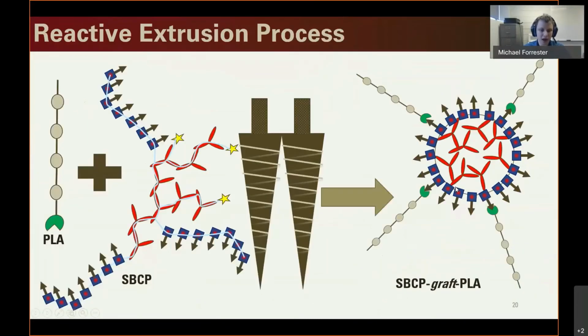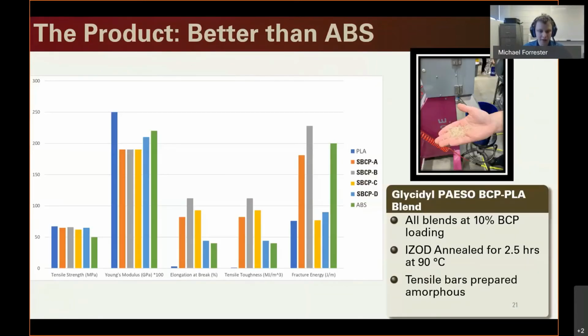And so that was then compounded in the Haake system with polylactic acid. And the thought was that if we were doing what we wanted to, the reactivity of these glycidyl groups here would allow grafts of PLA to form, and some nice micelles with good interfacial interaction would be generated. And the mechanical data certainly seems to support that that is occurring. And this particular plot shows a couple of different formulas of that block copolymer we produced. These are increasing glycidyl initial molecular weight blocks. These are all at about 13% glycidyl methacrylate, and they are all loaded into PLA at about 10%.